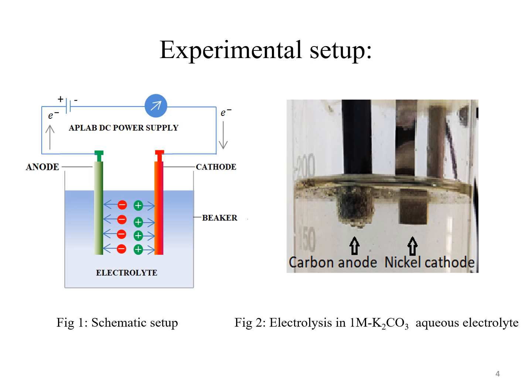Now, let us talk about the choice of the electrodes and electrolyte. For the anode, we use high quality graphite, which is 99.99% pure by WDS, in all of our experiments instead of noble metals like platinum or so. This is done to rule out the dissolution of anodic metal ions into the solution, thereby leading to electrodeposition on our working cathode, which we don't want.